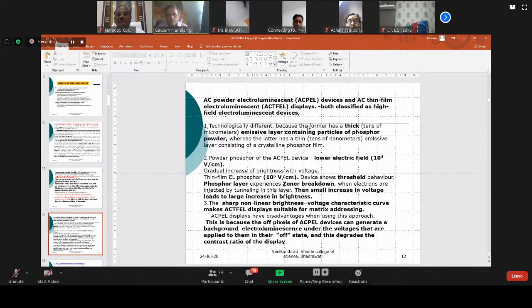AC powder electroluminescent devices and AC thin film are both high field electroluminescent devices. The technology is different. In powder, there is a thick emissive layer, thick meaning tens of micrometers, and a lower electric field, 10 power 4 volt per centimeter, with a gradual increase of brightness with voltage. In thin film, you have to apply 10 power 6 volt per centimeter. There is a threshold behavior. There is a Zener breakdown. The phosphor layer experiences Zener breakdown. When an electron is injected by tunneling into this layer, there is a nonlinear increase in brightness with voltage. The sharp nonlinear brightness-voltage characteristic curve is what makes AC thin film electroluminescent displays better than powder electroluminescent displays.